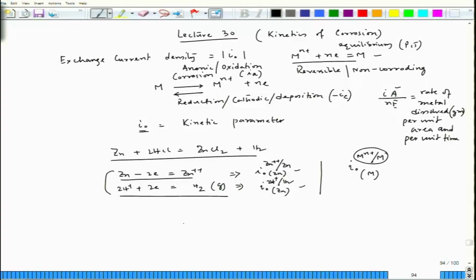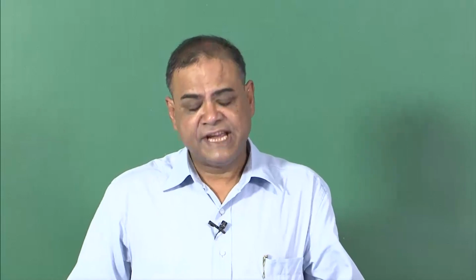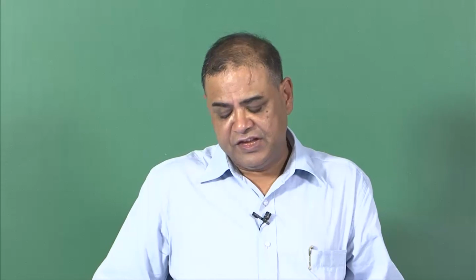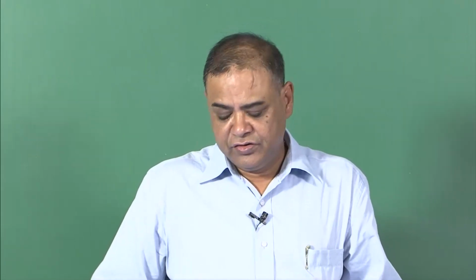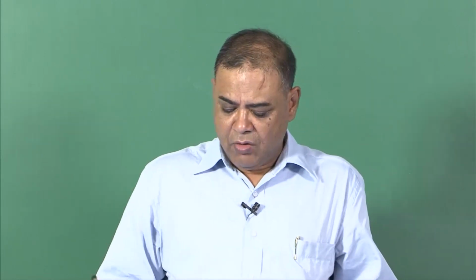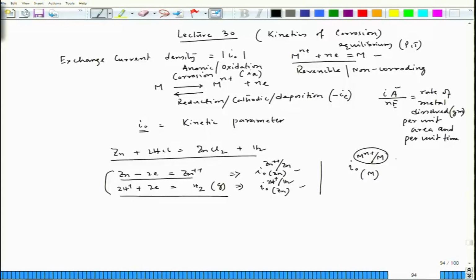For example, in this zinc case, zinc dissolution is taking place from the zinc surface, and that is what we are considering I0 for zinc dissolution on zinc, as well as hydrogen evolution is also taking place on the zinc surface. That is what we are considering, hydrogen evolution exchange current density on zinc surface also. Now, when we consider this, another important aspect is, since we are considering the material aspect, of course, this exchange current density would depend on materials.